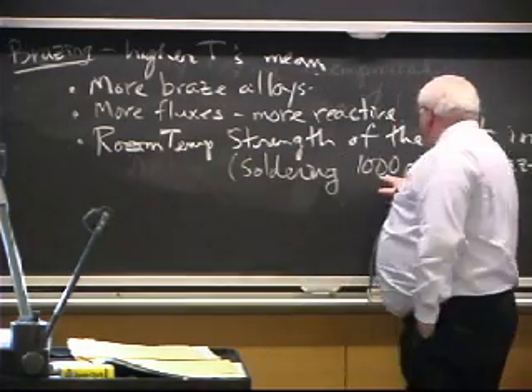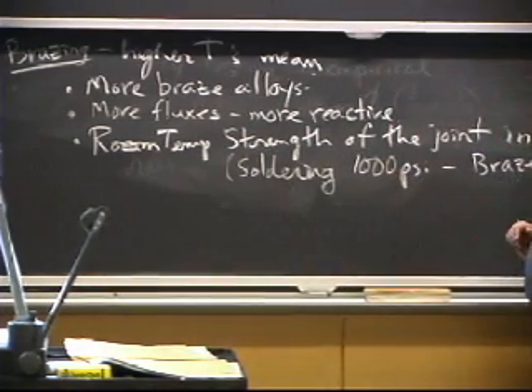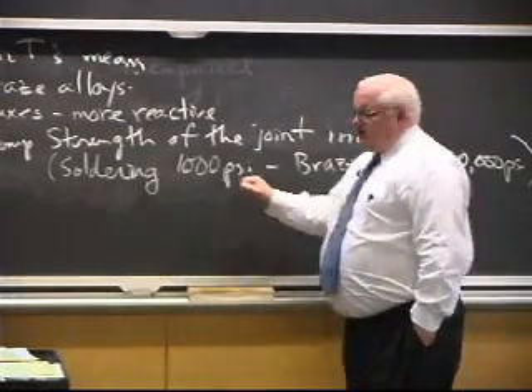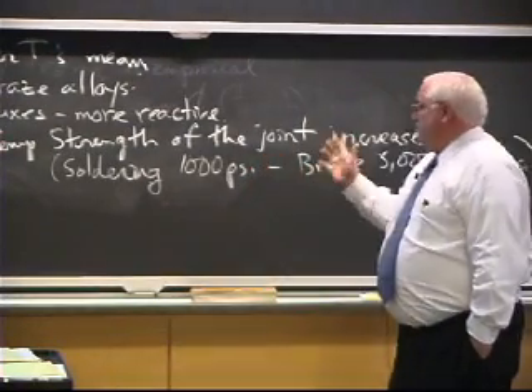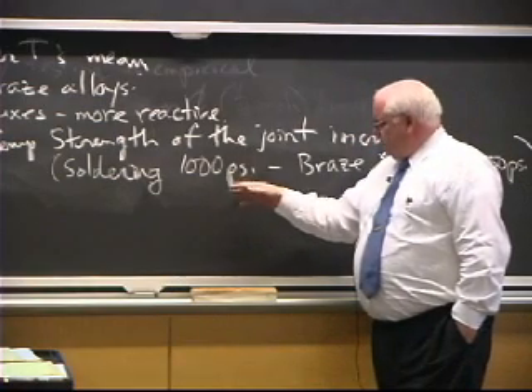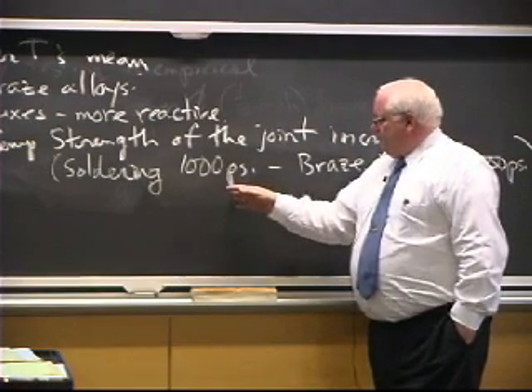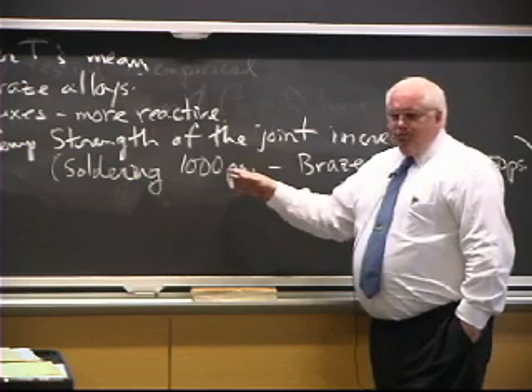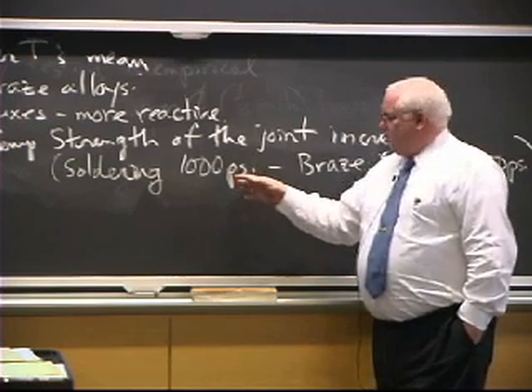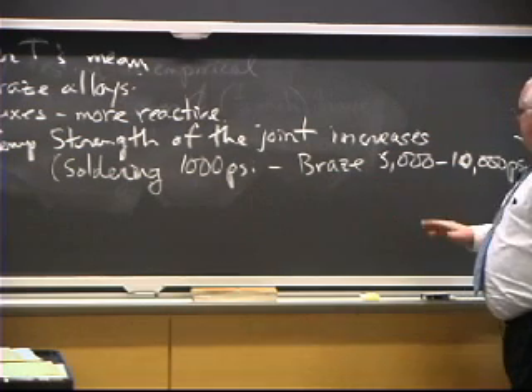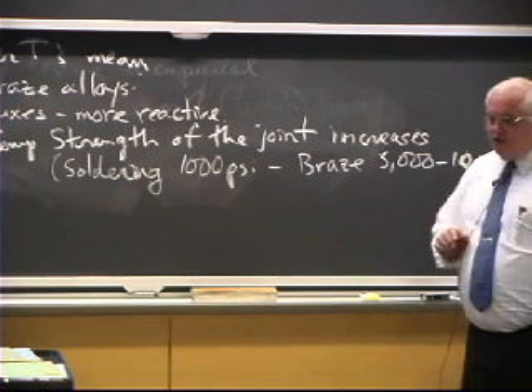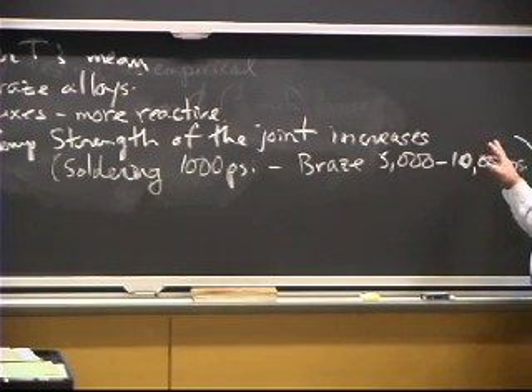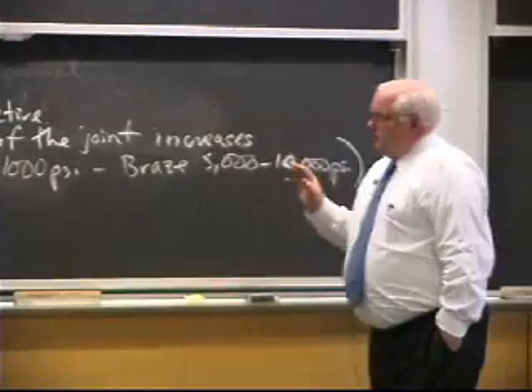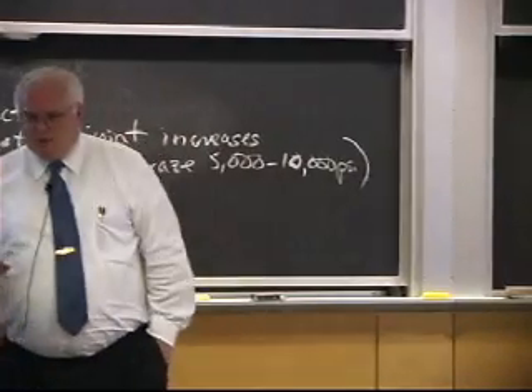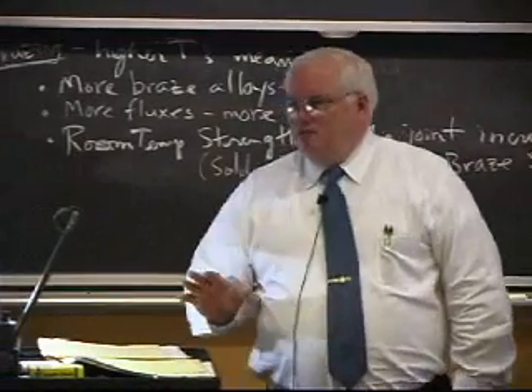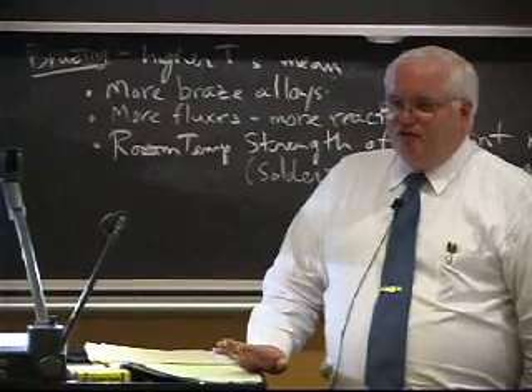Okay, so 1000 psi when you're at least 100 degrees centigrade below the melting point. What's a typical strength of an adhesive bond joint? Well, they're all over the place depending on the quality of the adhesive bond and the cleanliness of the surface, the type of adhesive. But a good adhesive bond joint might be 2000 psi. Okay? It could be 5000 psi in some cases. Brazed joints are typically 5000 to 10,000. I have seen brazed joints at 40,000, and we'll talk about how you can get some higher strength brazed joints. But just in general, don't rely on making brazed joints on a regular basis at 40,000 psi.